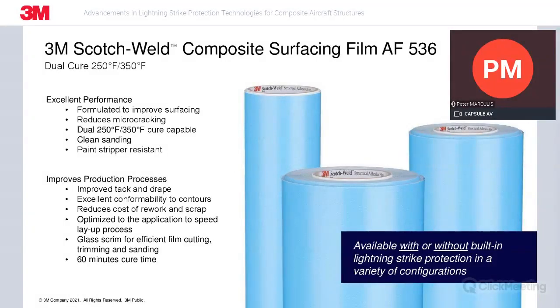In fact, we've incorporated a glass scrim that you see here in this material to help with the handleability, but it also controls the formability of the conductor itself, and it creates an additional barrier from sanding processes. In addition to this, we've really focused on a formulation that can help improve surface finish and minimize or possibly eliminate any imperfection you may have now in your process. It has also been tested for chemical resistance with different solvents and paint strippers. And then finally, it is available with and without a built-in lightning strike.